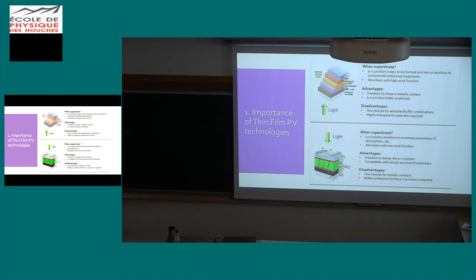Superstrate configuration is when you illuminate from the top of the solar cell, from the opposite side of your substrate. This is much better when your PN junction is sensitive to parameters like temperature, atmosphere, etc., and with an absorber with a low work function, where producing an ohmic contact is quite easy. The advantage is you have a lot of freedom to design your PN junction because the absorber was already synthesized when you start to build your junction. It's compatible with almost any kind of substrate, so you don't need specifically a transparent substrate because you are illuminating in that way. The disadvantage is you have few choices for metallic contacts that can withstand the temperatures and the conditions for synthesizing the absorber. And finally, you need better protection of the PN junction because the PN junction is closer to the atmosphere.